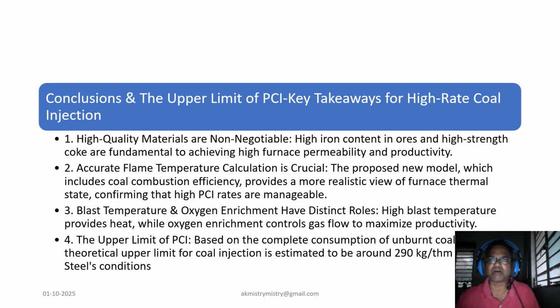The experience at Baosteel suggests that an oxygen enrichment of 1.5 to 2% is reasonable for PCI rates over 200 kg per ton hot metal, especially when blast temperatures are already above 1200 degrees centigrade.